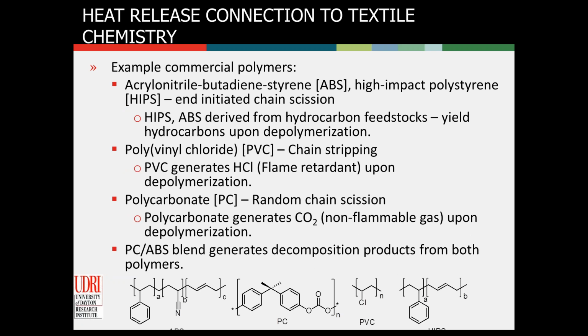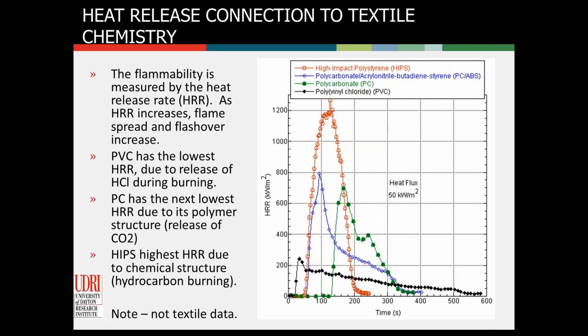There's ABS, polycarbonate, PVC, and high-impact polystyrene. And you look at a cone calorimeter, and the heat releases are entirely different from one another. High-impact polystyrene is a very high heat release rate material. Not surprisingly, it's an aromatic hydrocarbon. It's not that different from solid diesel fuel, if you want to think about it, and it burns pretty intensely. Polyvinyl chloride has a built-in flame retardant, chlorine, in every repeat unit of its structure. Not surprisingly, it's going to have a low heat release.